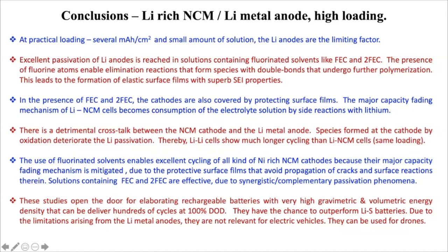The use of fluorinated solvents enables excellent cycling of all kinds of nickel-rich NCM cathodes, because their major capacity fading mechanism is mitigated, as I demonstrated, due to the protective surface films that avoid propagation of cracks and surface reactions therein. Now, the solutions containing both FEC and 2FEC are effective due to synergistic and complementary passivation phenomena. First by 2FEC, and healing during prolonged cycling by FEC.